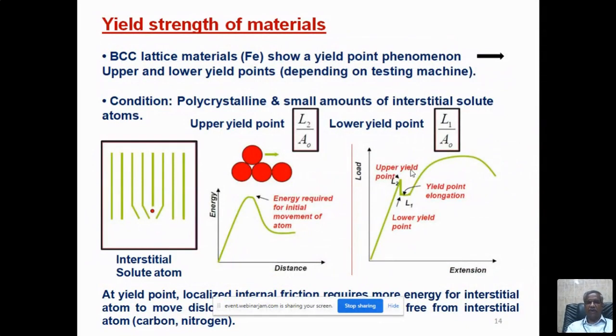This will occur only in a few materials, even in steel, low carbon steels will show this yield point phenomenon. And then the stress strain curve will take its original deviation. So here, no need to apply the 0.2 or 0.1 offset yield strength concept. Directly you can take the upper yield point as the upper yield strength, and the lower yield point as the lower yield strength, and the average in between you can take as the yield strength or yield point of the material.